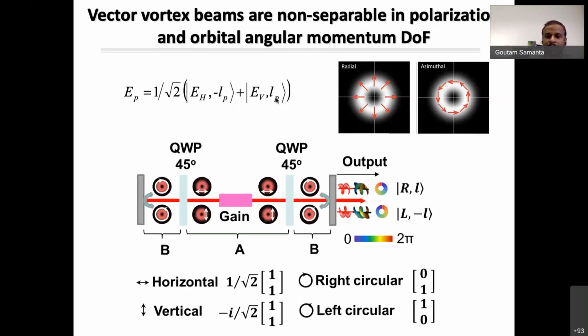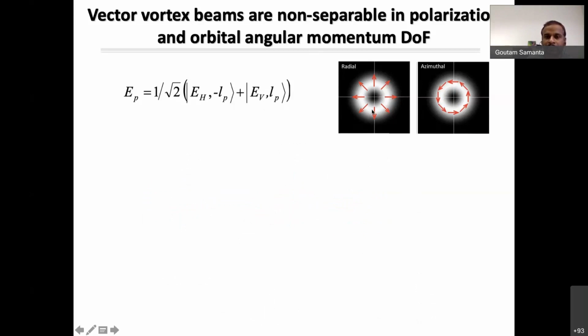But nonlinear interaction, as we say with momentum conservation, is basically a single polarization effect. If you select a nonlinear crystal and phase matching, that works for a particular polarization state. Let's say we have designed the nonlinear crystal for vertical polarization. If you have a horizontal polarization in the pump, that will be unchanged and unaltered.